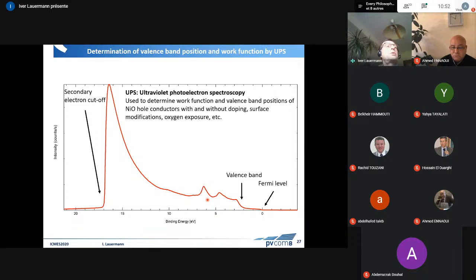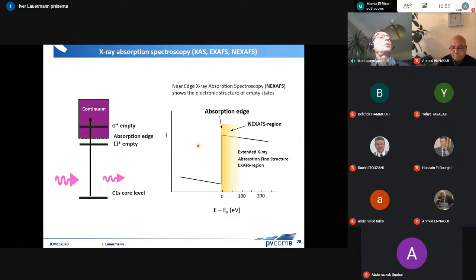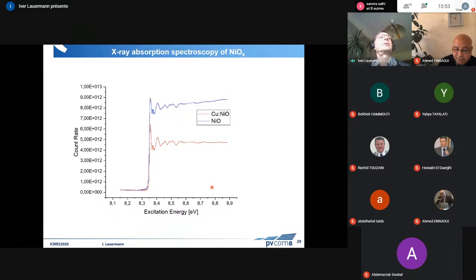We can also use ultraviolet light, then we call it ultraviolet photoelectron spectroscopy. And here we can determine the work function of the material, the valence band position, which is crucial for the setup of the whole cell. We use the synchrotron for X-ray absorption. And there we look at the absorption edge of a certain material, for example, in this case, nickel oxide. And these are data that we just got last week at a short beam time at the BESSY synchrotron.